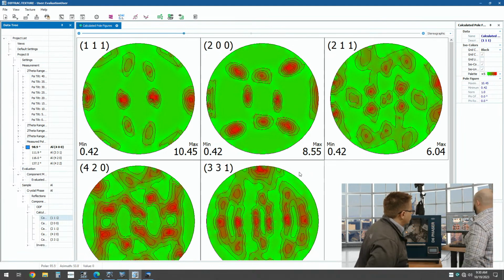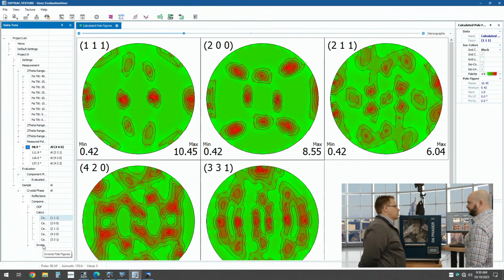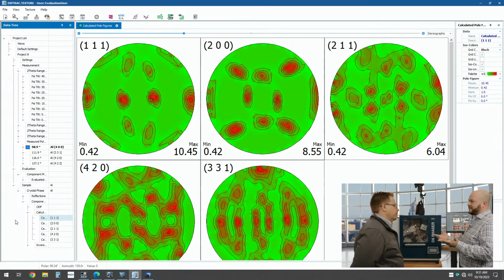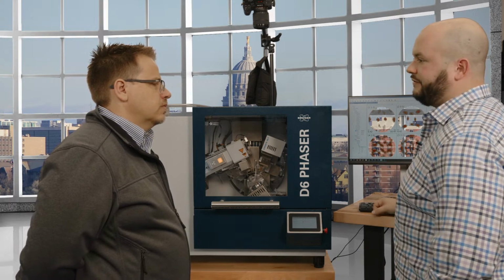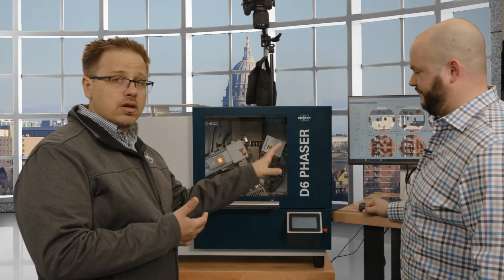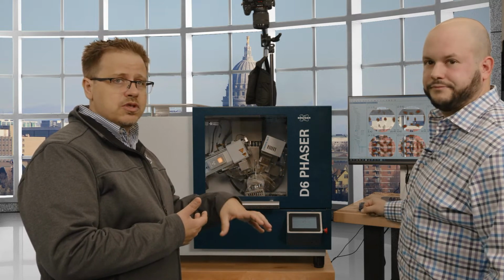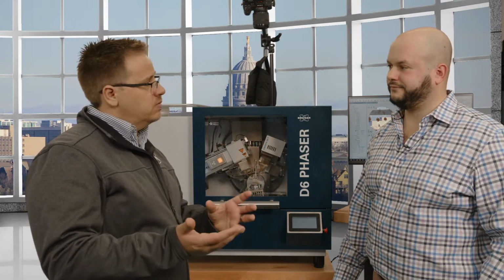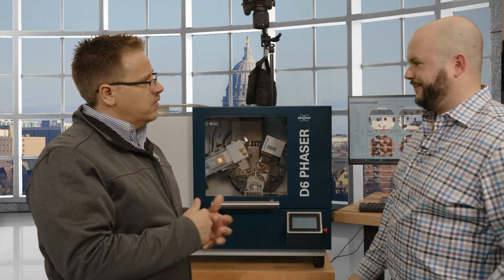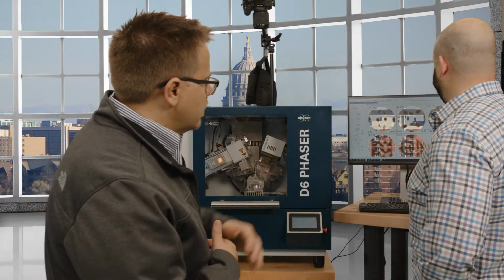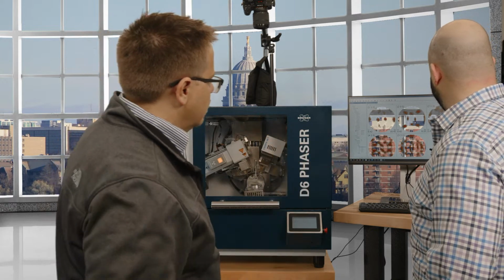One thing that's really important for this analysis is that we use what's called the component method. It's based on modeling, and we use elliptical broadening in this case to calculate the ODF. So instead of spherical harmonics, which is the method that just uses different mathematical functions, here we're fundamentally fitting the data using different texture components. The benefit is that it gives you a direct correlation back to the material. It says, I think this many grains are pointing in this direction with this amount of variability. And like you said, the reconstructed pole figures fill everything in, edge to edge.